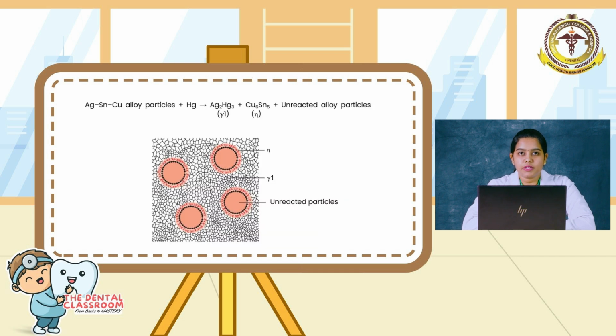The alloy particle components react with mercury to form gamma 1 phase and eta phase, and some amount of unreacted alloy particles are also formed during the reaction. The microstructure of set unicompositional alloy has no or very little gamma 2 phase, and eta crystals are more distinctly formed in unicompositional amalgam than in admixed alloys.